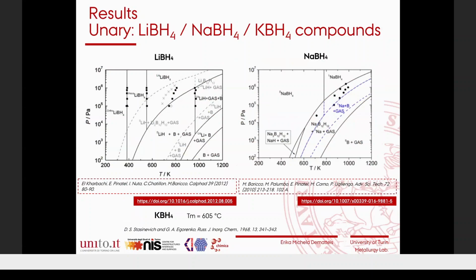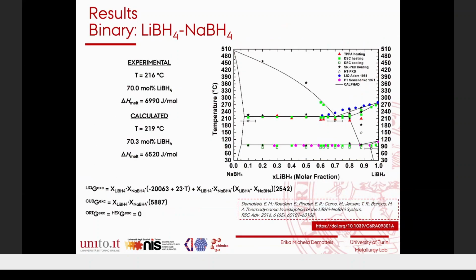Regarding complex hydrides, the results I will show you today start, of course, from the description of unary and pure compounds. So in the case of lithium, sodium, and potassium borohydride, we published in the last year the thermodynamic databases of these pure compounds. Some assessments were still missing for potassium borohydride, but as you can see in the graph, we described the phase diagram as a function of pressure and temperature of lithium borohydride and sodium borohydride. And this allowed us to understand the phase stability and also the hydrogen evolution mechanism and reactions involved in different pressure and temperature ranges. Furthermore, we extend the investigation to binary systems.